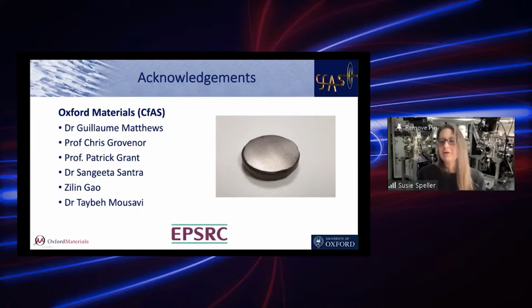So the FAST process puts on some pressure, at 50 megapascals, which does help to reduce the magnesium loss. I'm not entirely sure, because of course it was my students that did this. I don't think we looked for any magnesium at the surface, but for sure we get some excess magnesium left in the bulk if we add too much.